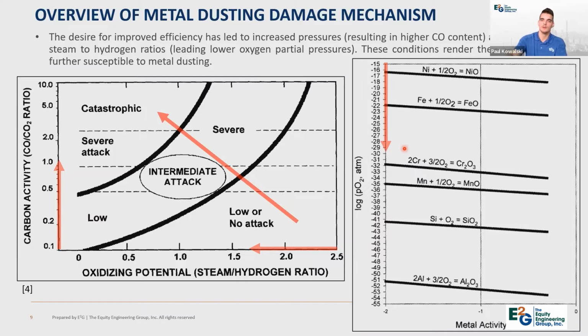So the graph here on the right shows the relative stability of several common oxide layers versus oxygen partial pressure. So as you can see, as oxygen partial pressure reduces, a nickel oxide layer, for example, would be the first to go or not be stable anymore. And as you go further down, additional oxide layers would become unstable as well as that oxygen reduces. And then we can also see from this graph that silicon oxide and aluminum oxide are two of the more stable oxide layers, relatively speaking.